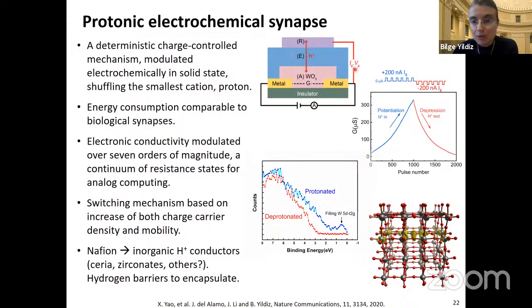And not only that, we could demonstrate it as a device that could emulate synaptic potentiation, but we could also explain the mechanisms based on charge carrier density increase as well as mobility increase. And we're continuing to work on this device to optimize its device design configuration, but also explore alternative materials, especially replacing Nafion with completely inorganic proton conducting electrolytes, and also encapsulating this device to block hydrogen escape.